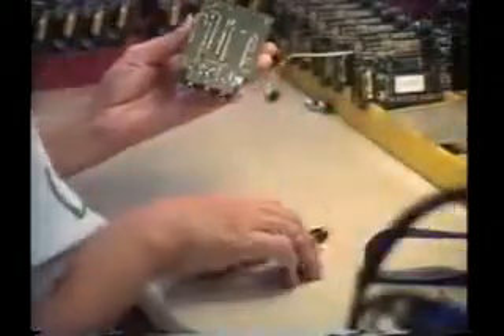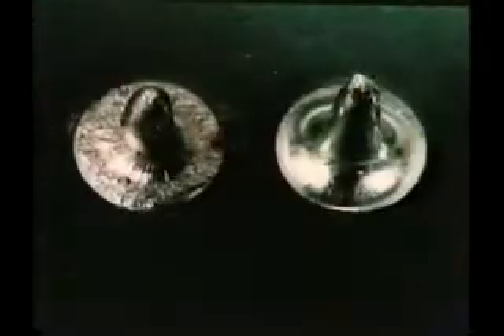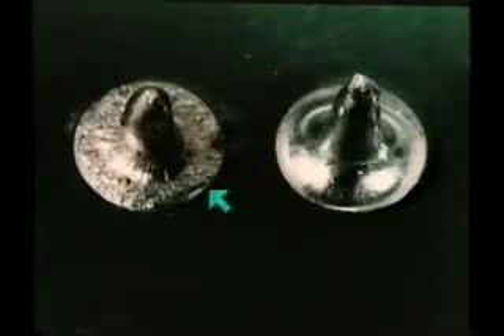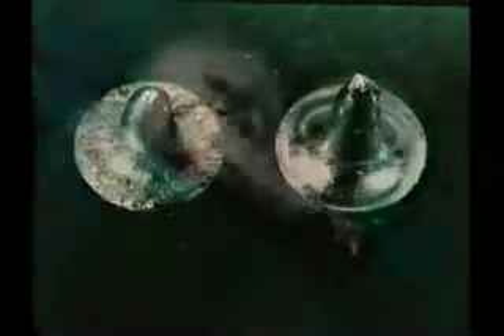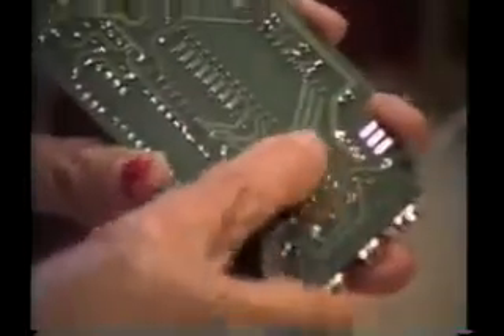This is a disturbed joint. Either the board or the component was moved during the solidification of the solder. It's important to keep the board and the component stable during the cooling of the solder. You can see that the solder is dull and grainy, similar to the cold solder joint. This is a fractured joint. The lead may have been moved after the solder hardened. Clipping the lead too close to the solder can also fracture the joint.